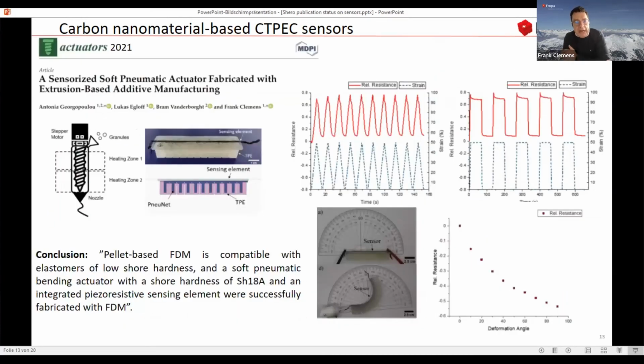Then after a while, we found a way to also process soft materials, and this is what you can see here. What we did is we used a pellet extruder, and with the pellet extruder, we could nicely produce very soft materials. These properties were similar to normal silicone, so we can come down to a shore hardness below 20A, which is in the range of Ecoflex or the Dragon Skin, which is normally used.